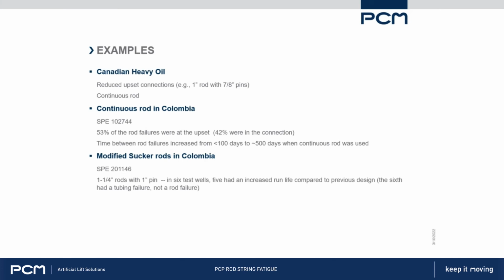So when they use continuous rod, of course, they don't have connections anymore, and they don't have these rod fatigue failures, or nearly as many. The time to rod failure increased from less than 100 days to about 500 days. So pretty good improvement there. The next paper is a more recent paper, and they're talking about this modified connection.